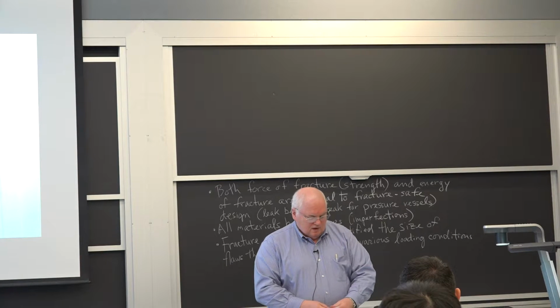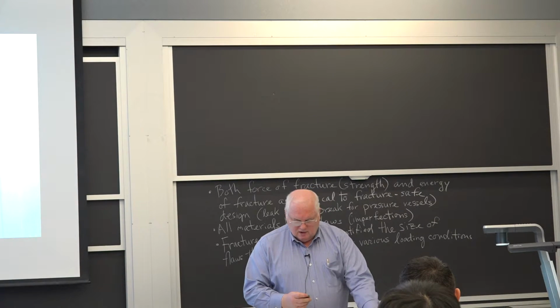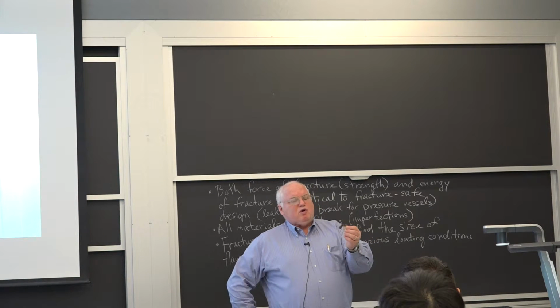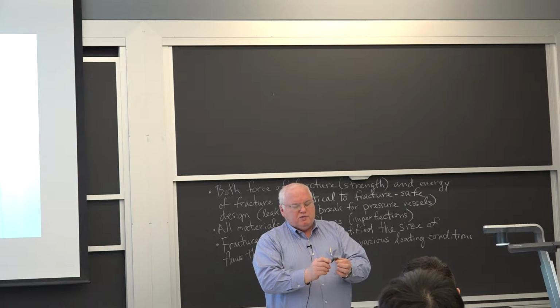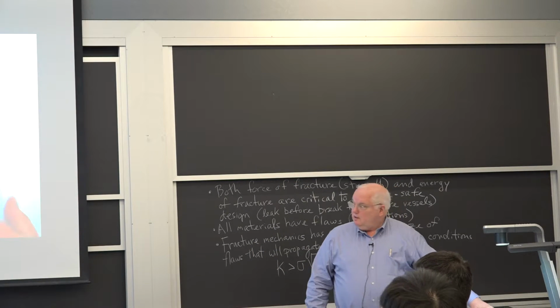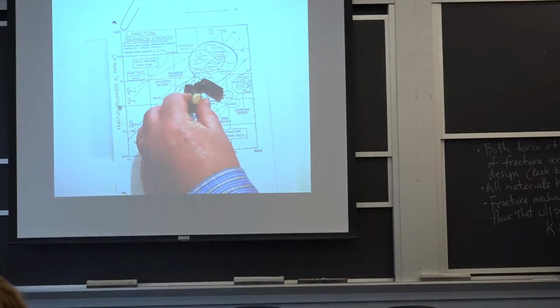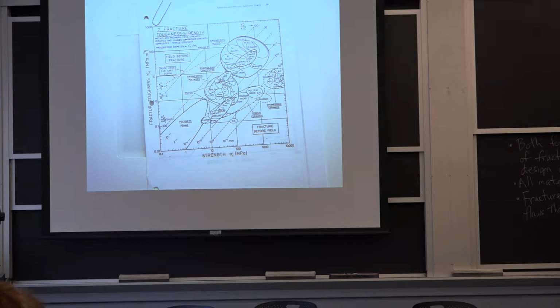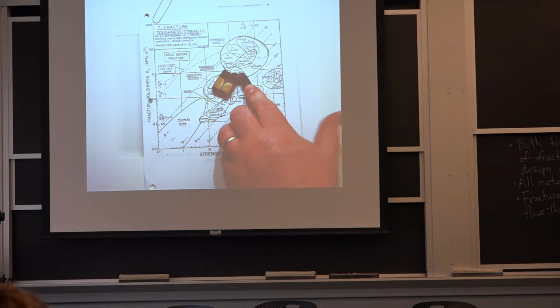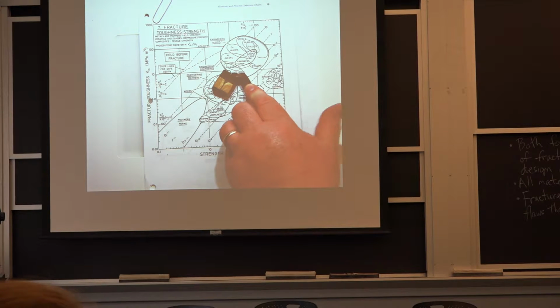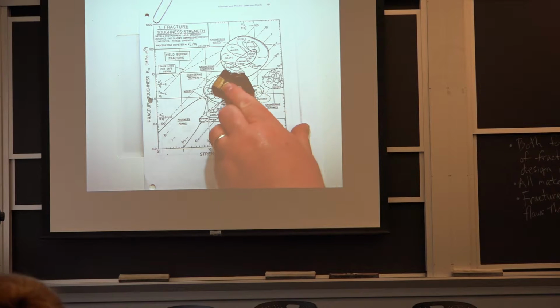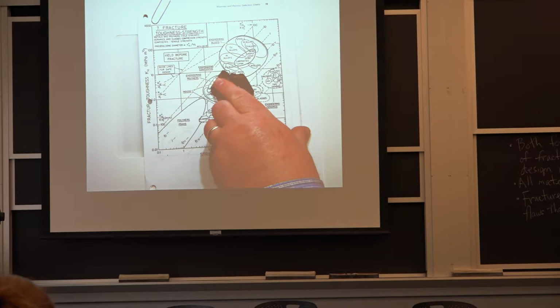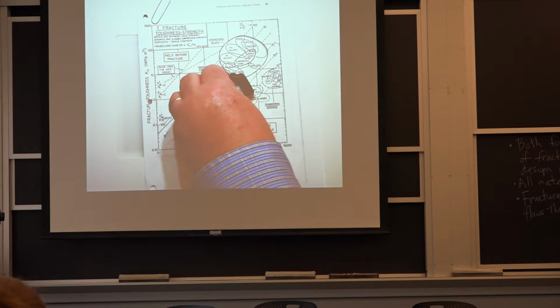Okay, so I'll pass this around. Here's a broken Charpy bar that was ductile and did not fracture all the way through, and so it forms sort of a V shape, okay? So there's the V shape. And here's another one that's shattered, not shattered exactly, it probably was sort of 5 or 10 foot-pounds. This one that bent like this probably stopped a hammer, a big swinging hammer that had 264 foot-pounds, okay? You don't want to be kicked by a horse at 264 foot-pounds, okay? It will break a few bones. If it hits you in the head, it will kill you, okay? But the other one probably fractured at 10 or 15 foot-pounds.